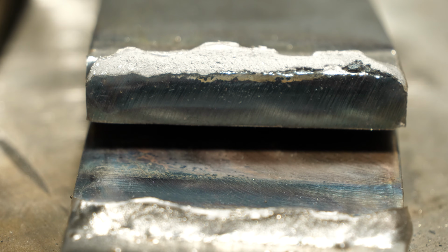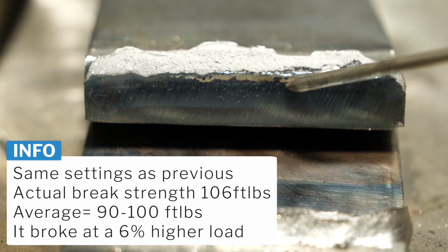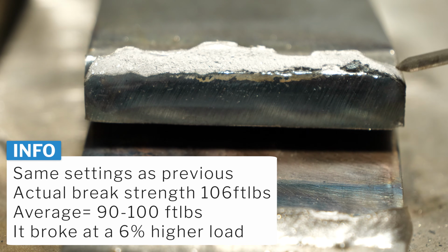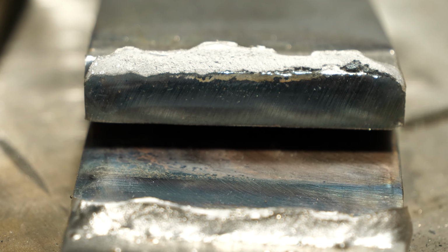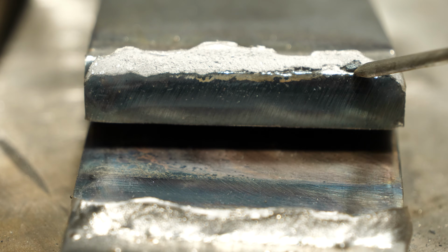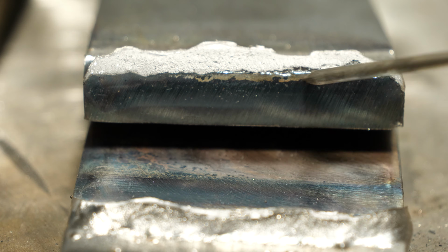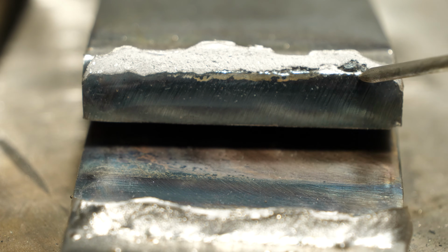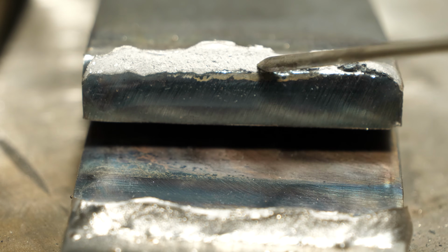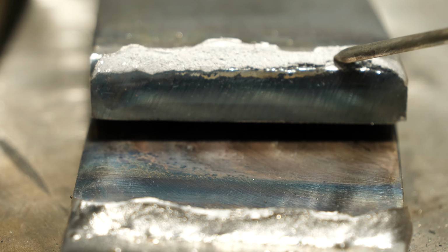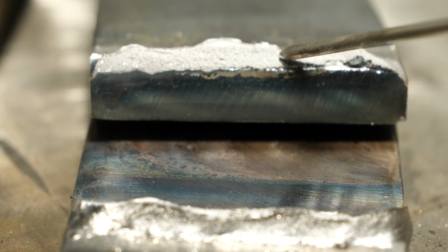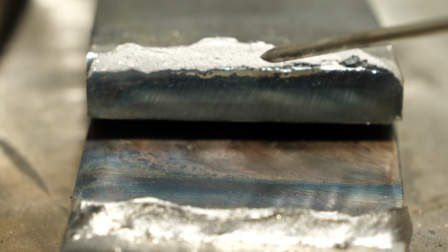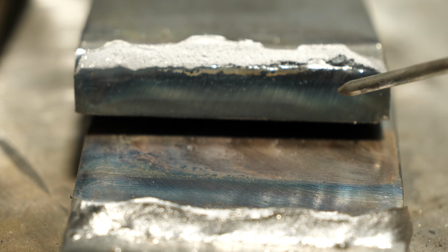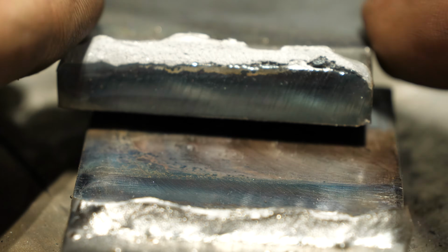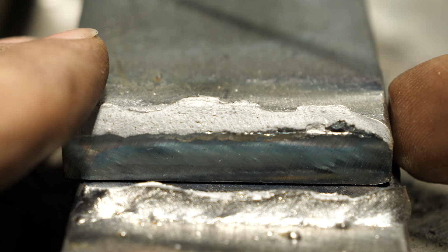This was preheated plates. When you look here, it still didn't fuse that well in at the start, and that's typical of MIG, and to be honest, of most welding processes. And in all of the testing that you hopefully have watched on my channel of stick welding, you'll notice stick tends to do the same exact thing, where the first about 1/2 inch, 3/4 of an inch of the weld tends to have poorer fusion than the rest of it. And that's typical, and that has to do with the fact that once it gets going welding, the fusion starts increasing due to the fact the plates are preheating in front of the direction you're traveling. Now there are ways that you can adjust for this, like with stick welding, you can, let me bring this better into focus there for you guys. Sorry about that.